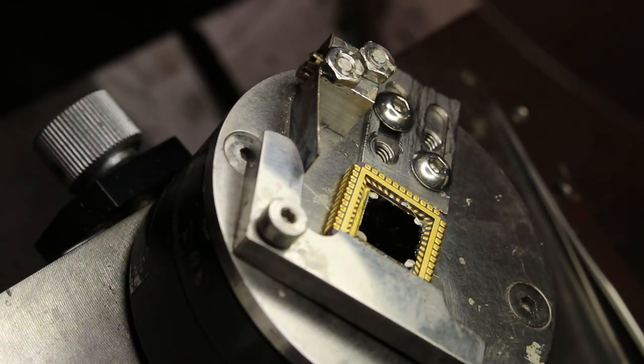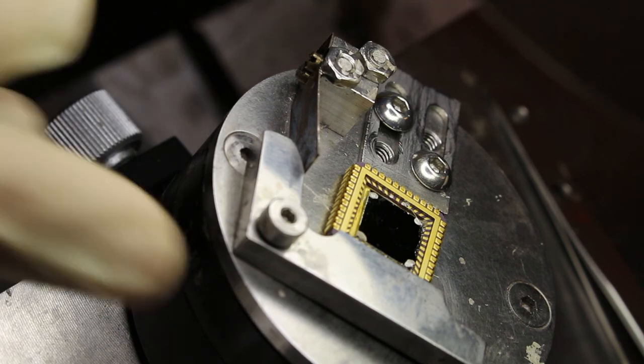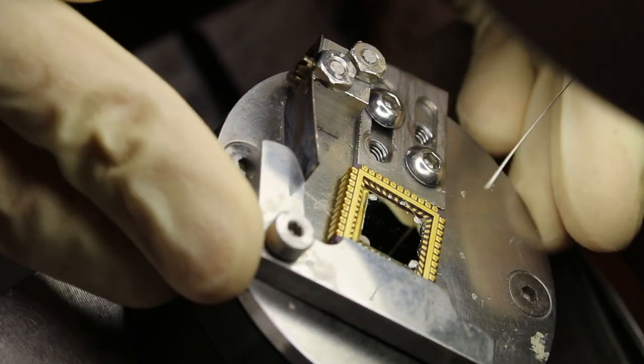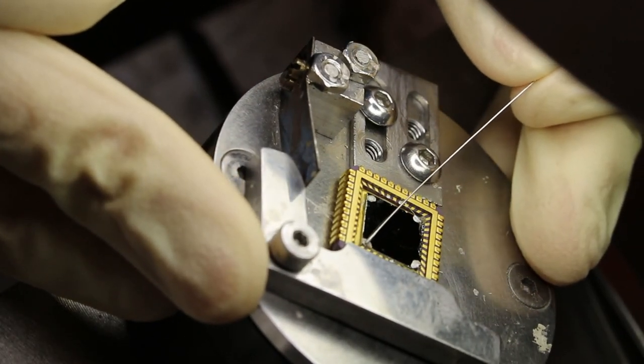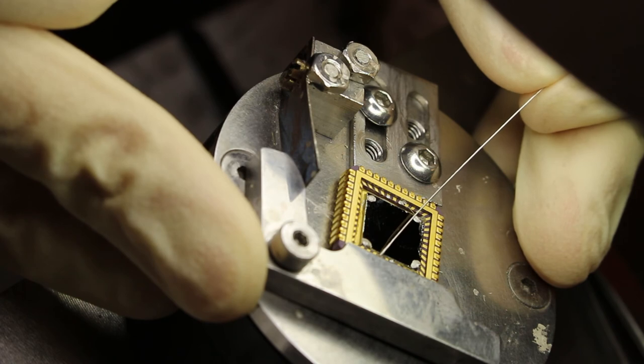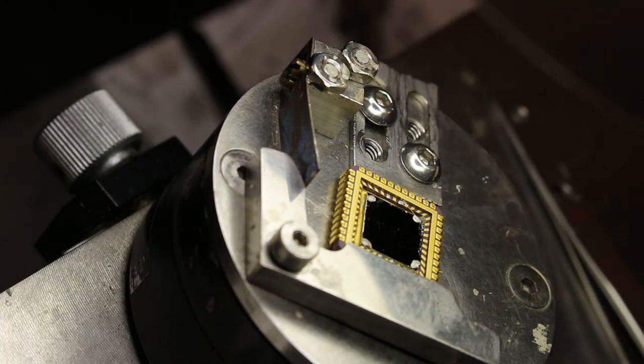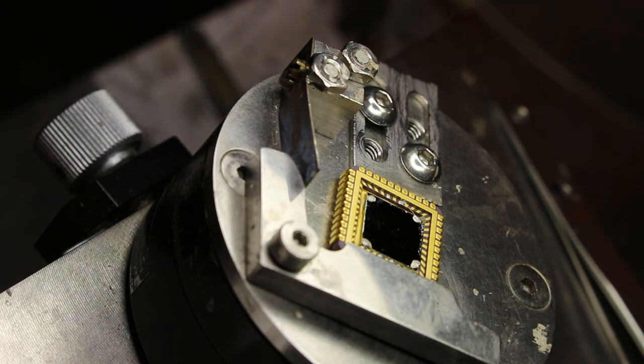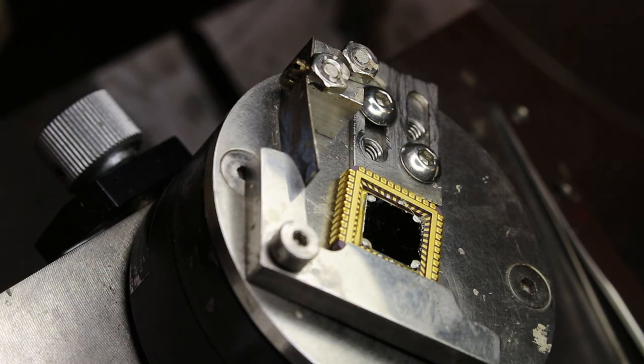I don't know if I mentioned this earlier, but when you're doing the wires, it seems to be important to actually get the end of the wire inside the silver paint. I don't know if that's because the wire has oxidized. That doesn't really make a lot of sense for gold or if there's some sort of coating on it. But the ends seem to be important in my experience to get low resistance contacts. So try to get the ends in there, but basically that's all four of these and all four of the other contacts. And that's all.